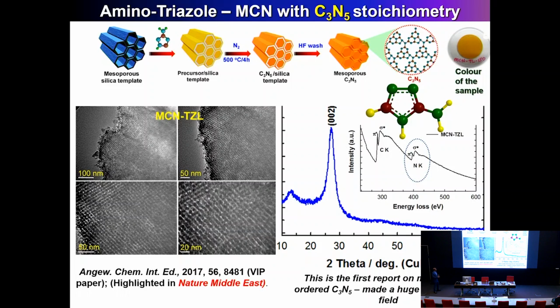analysis. And you see here from the TEM images, it has got a highly ordered porous structure. And from the electron energy loss spectroscopy, one can clearly see there is a huge increase in the intensity of the NK shell excitation edges. And from the shape of the CK and NK shell excitation edges, you can see that there is a strong bonding between the carbon and nitrogen, and they are sp2 hybridized. But the wall structures are amorphous in nature.